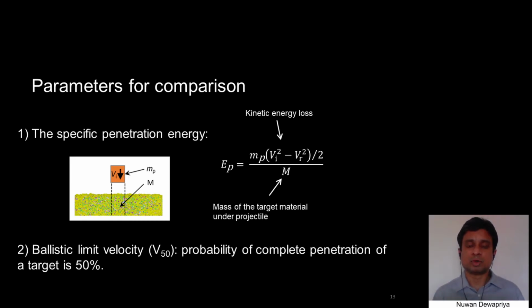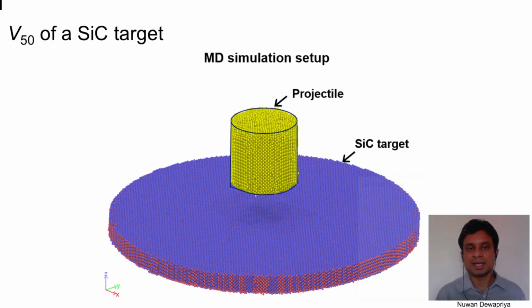Now we have a good model to investigate the impact resistance of nanoscopic multilayers, but we need some parameters to compare their performance with other materials. We can compute specific penetration energy, which is the energy absorbed during penetration, and the ballistic limit velocity, which is the velocity of a projectile when the probability of complete penetration is 50%. It is commonly referred to as V50. Here I am going to explain how we computed V50 of this ceramic target using MD simulation.